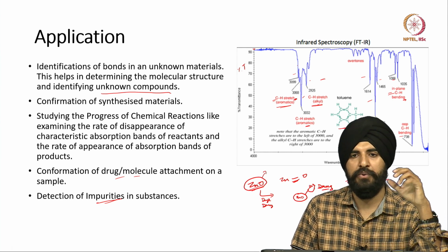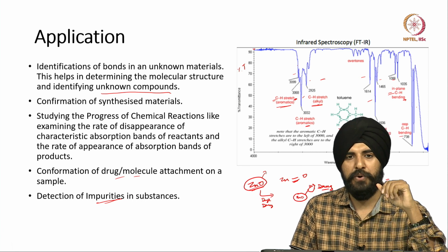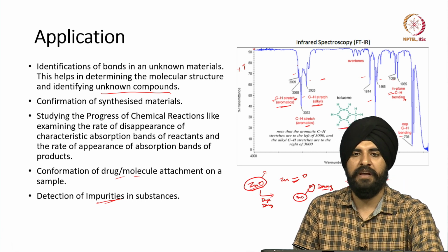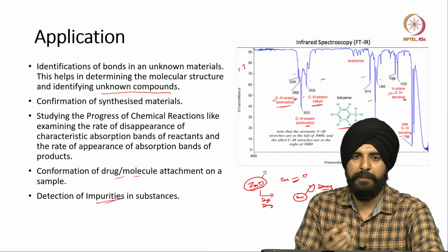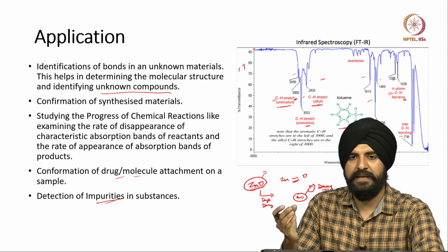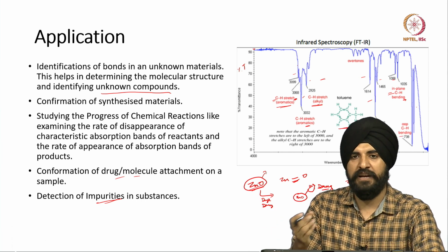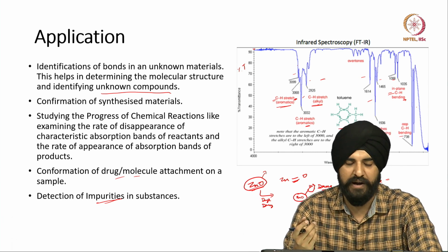So, supposing you have a silicon wafer and you do an RCA cleaning. So, you quickly run it through the FTIR or the IR spectroscopy to see whether all the impurities have been removed or not, and if IR detects any peaks, that means apart from silicon, if it detects any other peak, that means some of the impurities are present on the samples and more cleaning is required.